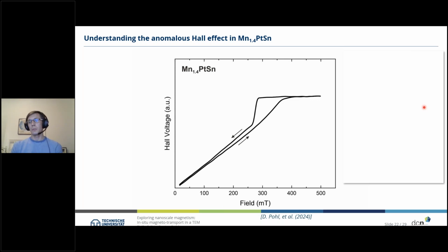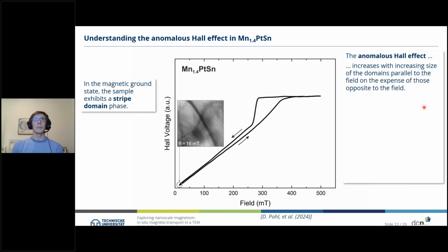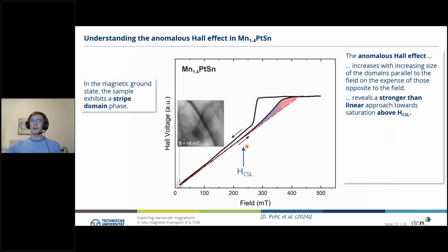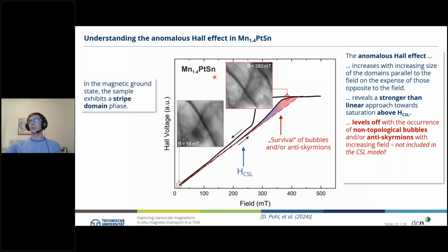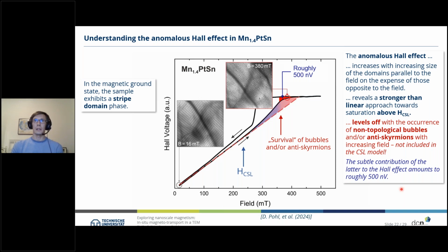So far we understand part of our hysteresis loop, starting from the magnetic ground state where we have a stripe domain phase which increases with increasing magnetic field. Then at a certain magnetic field value, we approach a stronger than linear increase of the Hall voltage, and that levels off with the appearance of non-topologic bubbles and anti-skyrmions with increasing fields. Of course, this is not included in the CSL model. This discrepancy where it levels off is of the order of 500 nanovolts. And this is what I want to discuss now in more detail.